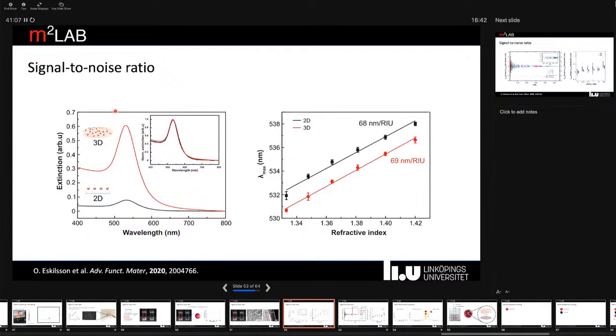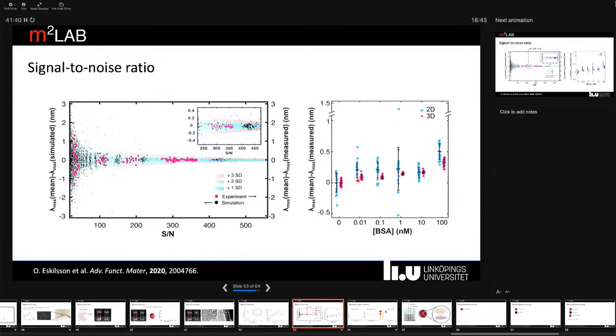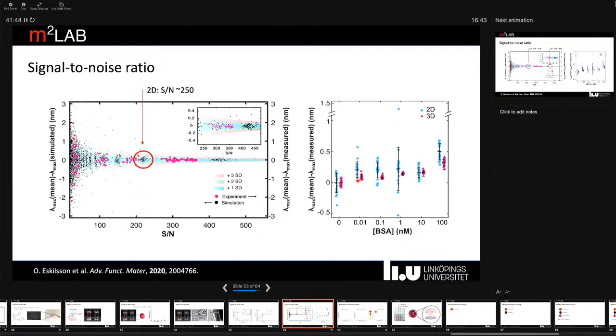And when we compare the intensity between these three-dimensional materials and the two-dimensional, we can see that there's a quite substantial difference here. But if we normalize the data, we see that there are no shifts or broadening of the curves. So essentially we have the same figure of merit, and this is also due to there being no differences in refractive index sensitivity here. So what this means is that we increase the signal to noise. For the 2D surfaces, we have a signal to noise ratio roughly around 250, whereas in this case, it's substantially higher, so around 450. And what this in practice means is that we have much better reproducibility when we measure things, because there is less influence from noise.